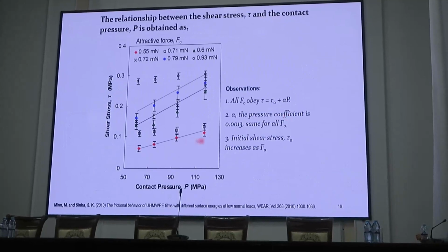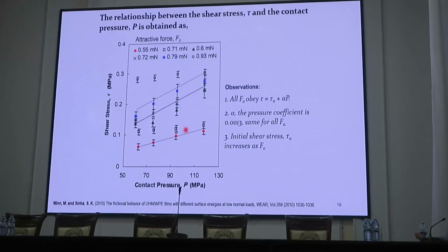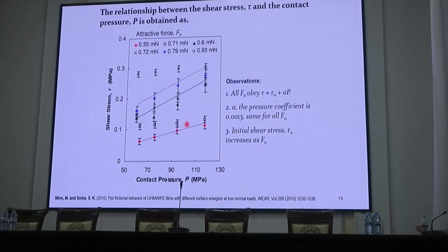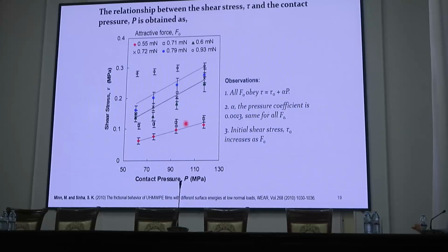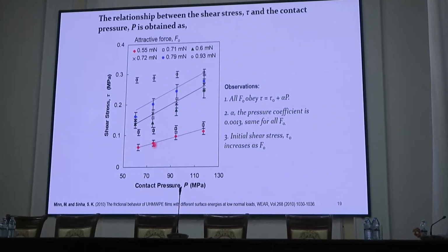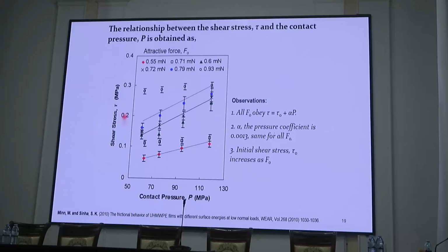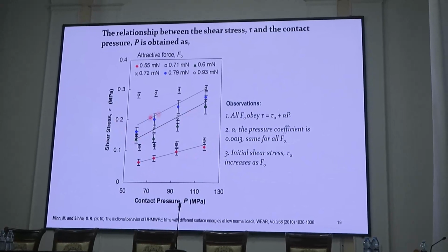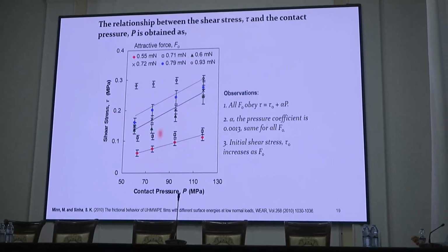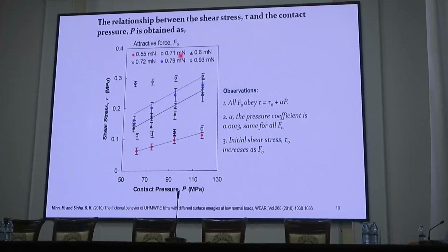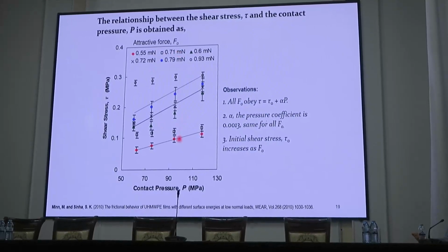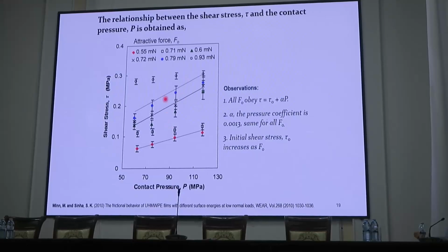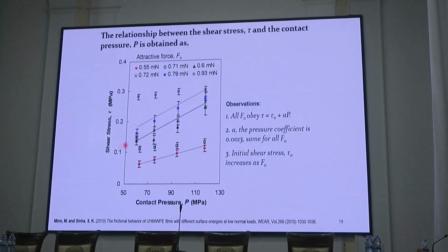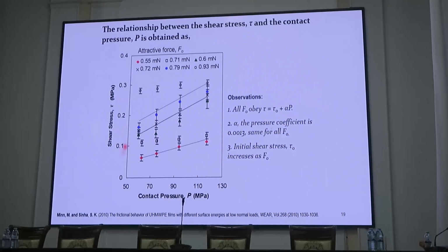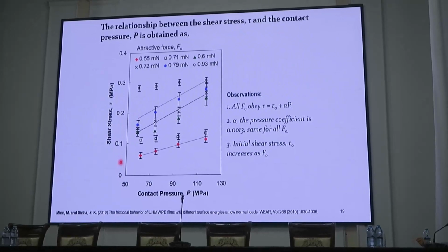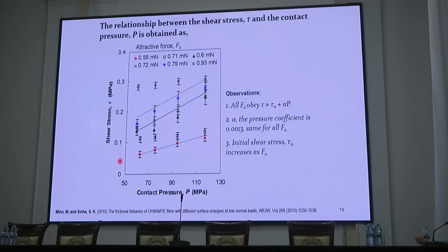In our work, we have studied UHMWPE sliding against a silicon nitride ceramic ball, and we find the same type of relation, shear stress as a function of pressure, but it does depend upon the adhesive force, that means the surface energy. As we change the surface energy, it changes. For higher surface energy, the intercept term is increasing. So it is dependent upon surface energy.